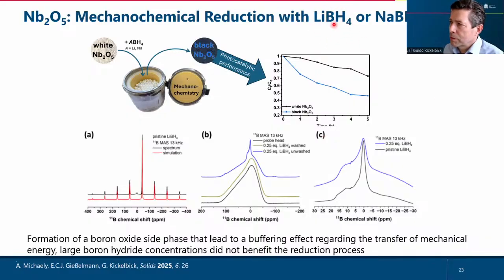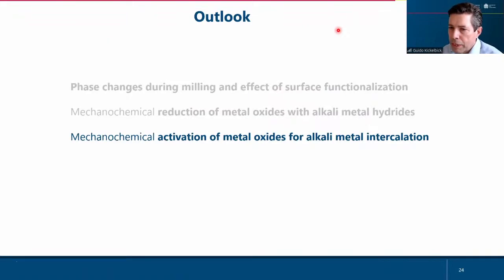Yeah, we of course tried also different other reductive agents here, for example, lithium borohydride or sodium borohydride. But if you do that with these reductive compounds, you always get not the same results as with sodium hydride or lithium hydride, because we think boron oxide is forming. We could prove that by boron solid state NMR. And this is a side product, and this, of course, reduces the mechanochemical impact in the reaction. So it's better to use the hydrides instead of using the borohydrides. Okay, last point.